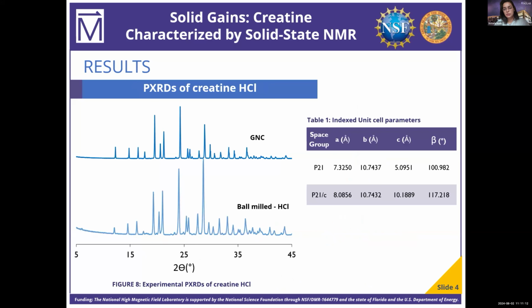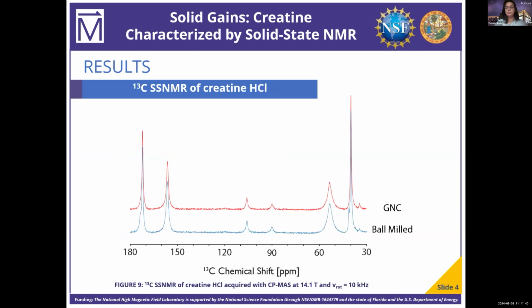For creatine hydrochloride, we compared the powder X-ray diffraction patterns of the commercial and ball milled samples and found they were in the same phase. However, there is not a known crystal structure, so this gives us an opportunity to use X-ray diffraction and solid-state NMR to work towards determining the structure. First, we indexed these PXRD patterns and found two likely space groups. This gives us some information about the arrangement of atoms in our crystal structure.